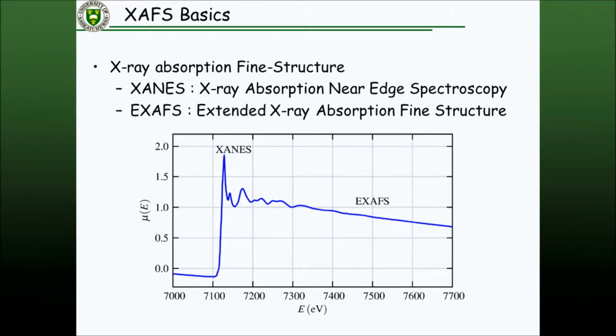And this tells us a lot about the coordination environment because the photoelectron is escaping and scattering off nearest neighbors of the absorbing atom. So it tells us how many nearest neighbors an absorbing atom has and what they are. And it turns out the frequency of this oscillation has to do with bond distances, how close the scatterers are, and the amplitude of this oscillation has to do with electron density, therefore what that scatterer is.